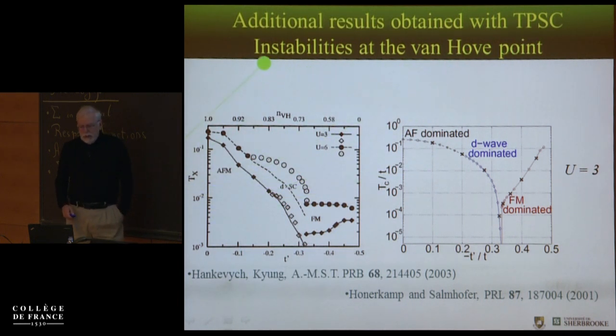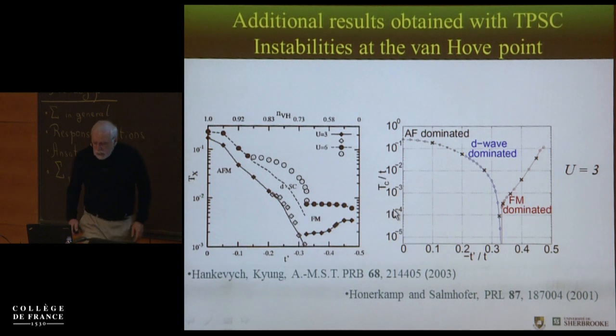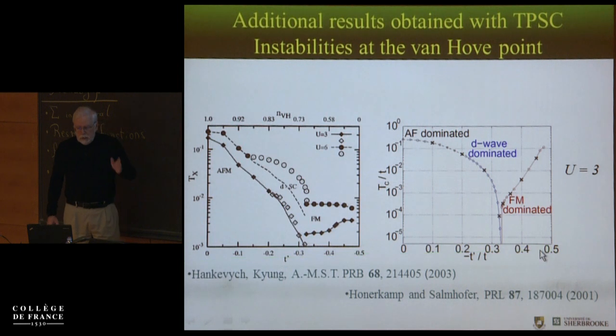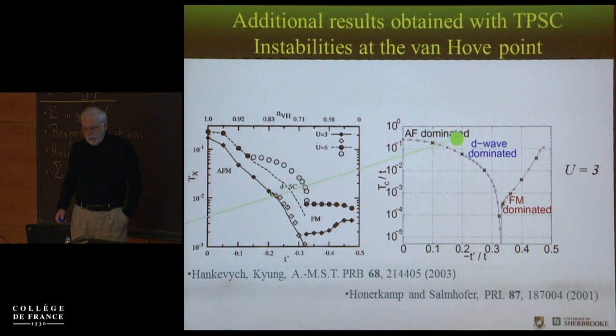How does it compare with functional renormalization group? We have to look to the right here. So this is a TC. This is the dominant fluctuation. This is when they lose control of the functional RG calculation, and that's as a function of T prime over T. So they change T prime, that moves the location of the Van Hove singularity, and they just choose the filling in such a way that they are right at the Van Hove singularity. So then they find that for small T prime, it's dominated by antiferromagnetism, then D wave, then ferromagnetism. And if you look at the same value of U equals 3 in TPSC, you get the same thing, antiferromagnetism, D wave, and ferromagnetism, but in a much cheaper way.